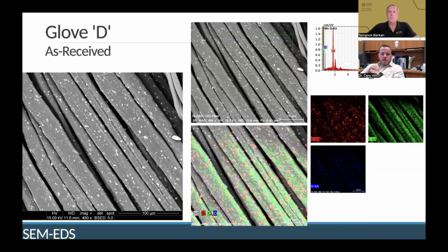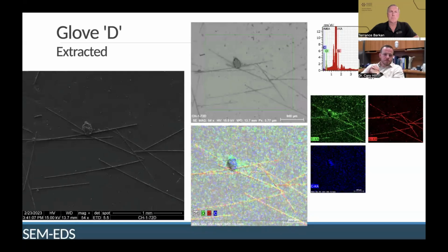Glove D was a different glove that had a couple of different additives in it. We saw a lot of silica present in this one, which again, that's fine. Just no graphene was evident by the morphological analysis. Next slide, Terrence. And what we did see though was a lot of glass fiber, which is just interesting. It's another traditional cut resistant additive. After we dissolved the fiber, we did not find evidence of graphene. What we found instead was other traditional cut resistant additives.